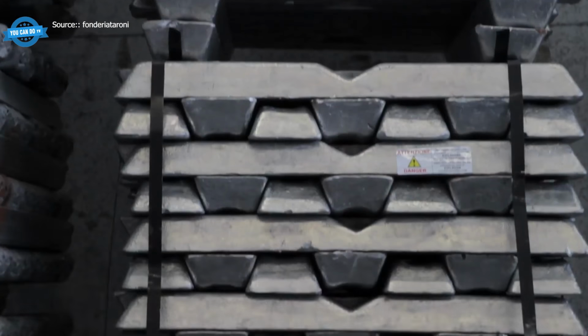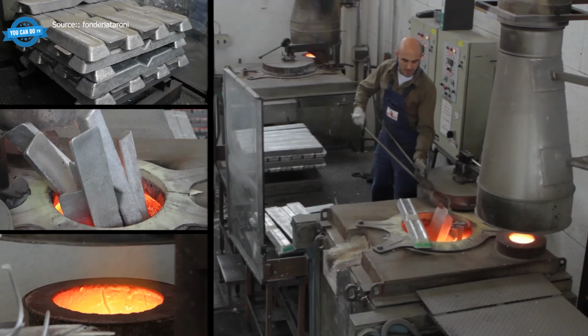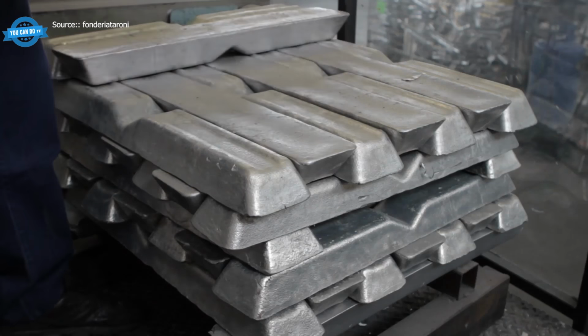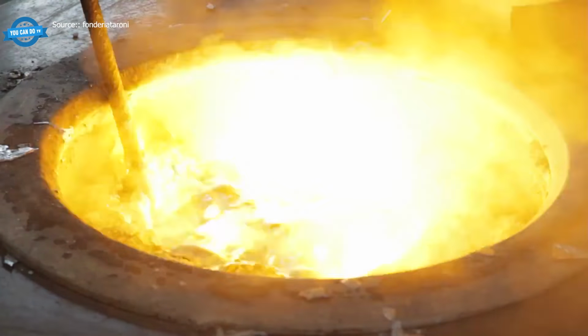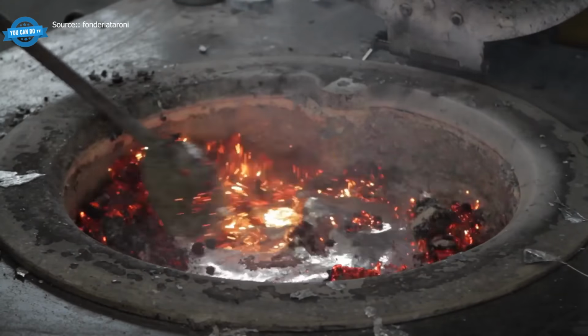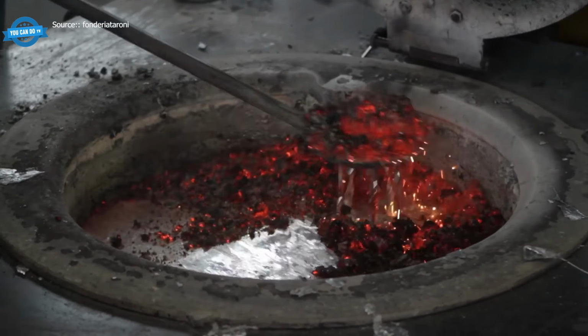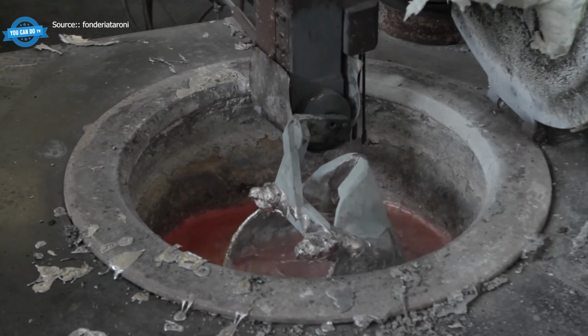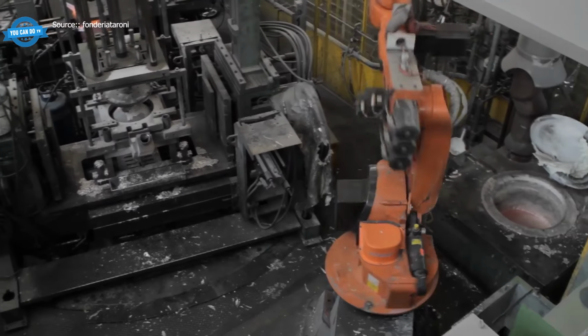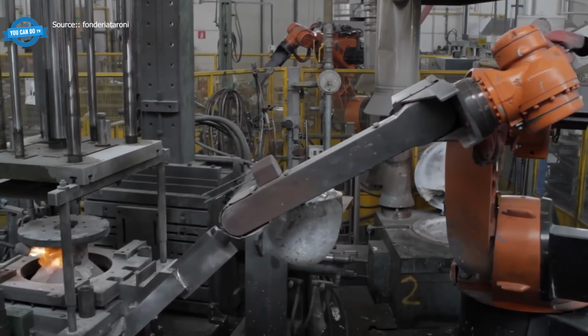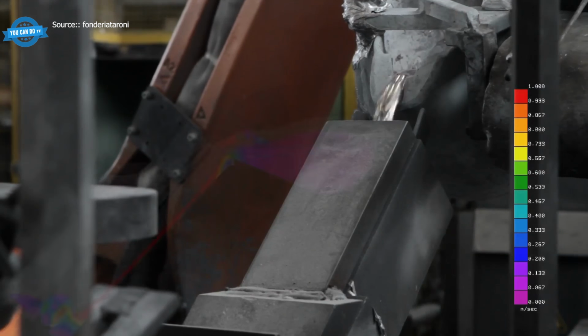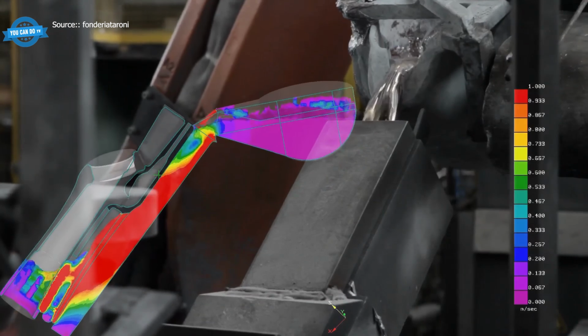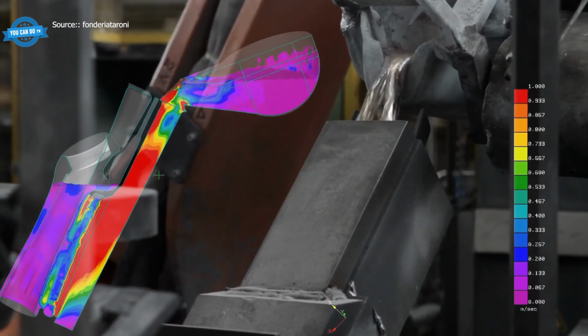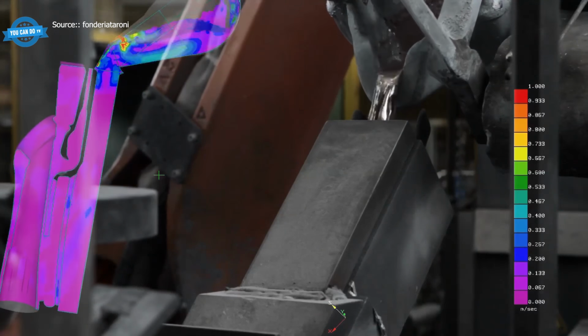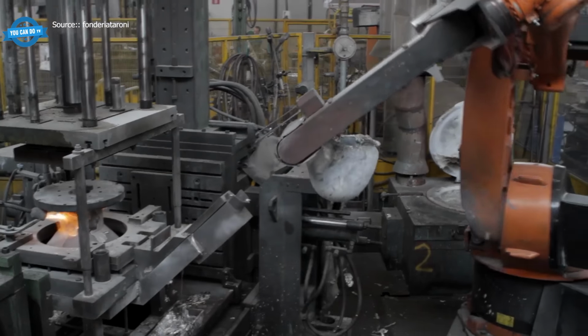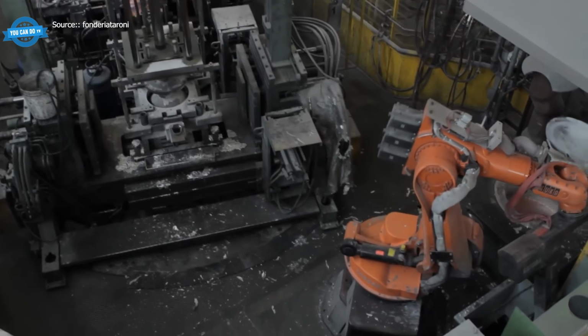Melting furnaces feed molten aluminum to holding vessels that keep the metal at the right temperature until it is needed. A worker periodically skims dross from the surface because oxide films trapped in the melt can weaken the casting. The casting robots pour into multi-cavity molds that produce several parts per cycle. Automation does not just make aluminum foundries faster, it makes them safer, since molten aluminum splashes are one of the more unpleasant things that can happen in an industrial setting.